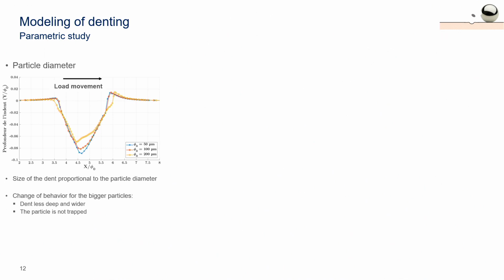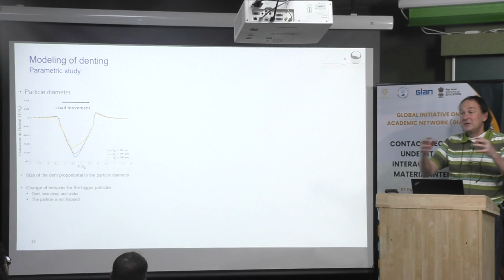Okay, then this is, for example, the effect of the particle diameter. What you can see, of course, here everything is dimensionless. Then if the particle is bigger, it means that the dent should be bigger. But in comparison to the diameter, because phi 0 here corresponds to the diameter of the particle, in fact there is almost no difference. Okay? Maybe here, but there is almost no difference, or very little difference, as far as the particle is smaller than the contact size. Because if it is bigger, you cannot create a dent, it will be different. Okay?